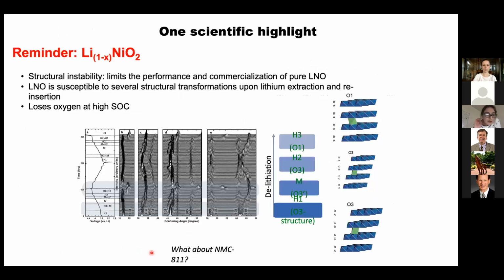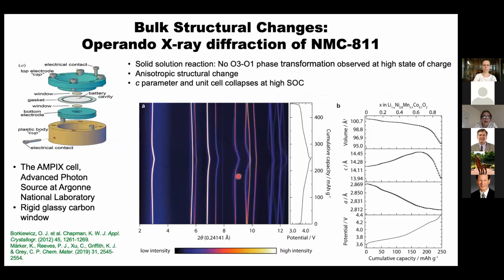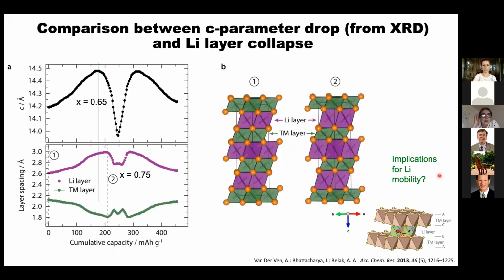Just to show you some examples of what we do, this is the cathode material lithium nickel oxide, which has a really complicated series of phases it forms as you remove lithium from the structure, and you can follow that with diffraction. But if you look at 811, it's much more simple. This is work we did a while ago using the AMPIX cell at the APS, where you can track the layer spacing, for example with this 1, 0, 0 reflection, and get the cell parameters. And there's no change in phases, so you have a continuous solid solution. But what's interesting is this massive decrease in the c parameter, which is the spacing between the layers. So let's reflect on that a bit more.